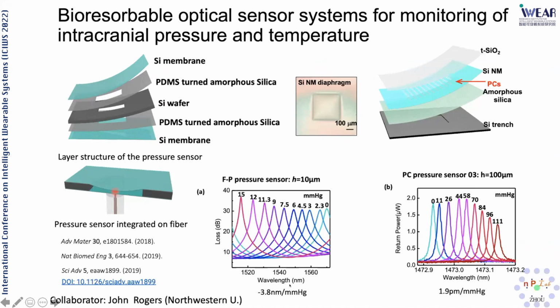Depending on the design and the range of detection and the sensitivity, you can choose to use a fiber cavity, especially if you want to look into a relatively large pressure range, or if you need a very high sensitivity measurement, then you can look into the photonic crystal cavity, where you can have a very sensitive tuning of this resonance here. Those are some of the work already published a few years ago. So that gives you a first part of background introduction about this photonic crystal platform we have been using with a goal.